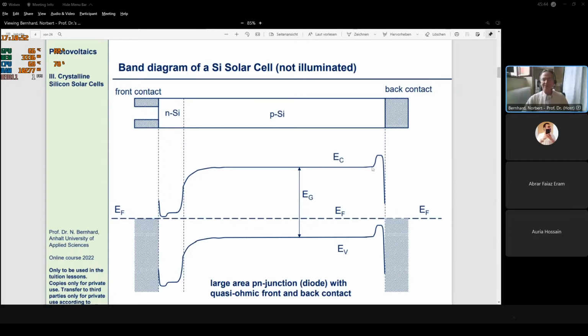And this is a sort of quasi-passivation there. It's not a real chemical passivation, it's a field passivation, an electric field passivation, which is better than nothing, but it's by far not as good as a real chemical passivation by a dielectric would be. And in the case of the PERC cell, here we have this passivation, and this is the reason why the performance of the PERC cell is clearly better than of the standard aluminum back surface field cell.